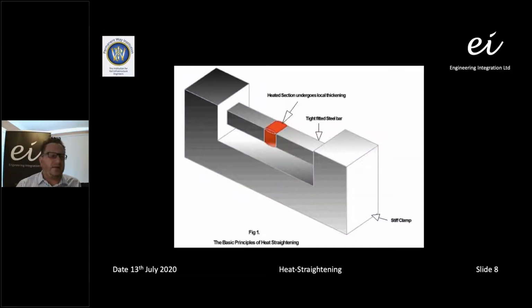So this is probably the most obvious way of describing how heat straightening works. Basically what we're doing there, you can see that there's a test piece in the middle of the diagram, and then there's a forged anvil, a sort of clamp that sits around the test piece. When we heat the test piece, it can expand in only two directions, in the X and Y directions. As it heats up, it obviously tries to expand, but it can't expand longitudinally. Therefore, as we allow the element to cool, it is able to cool in all three directions. Therefore, the steelwork effectively shrinks in the Z direction. And that's principally how we undertake heat straightening and the principles behind it.